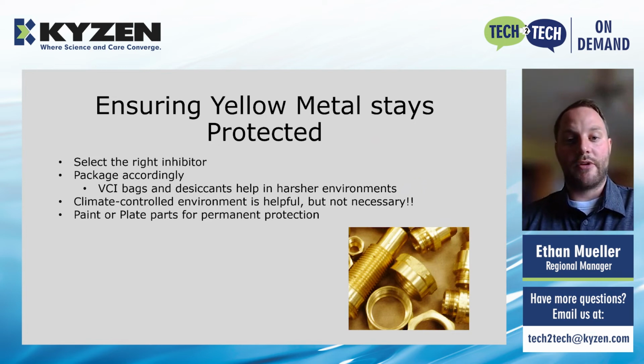And kind of the problem that you're having there is there's a good possibility that there's moisture on those parts, and the parts are hot, and so it's kind of like a humid environment trapped in a bag, and that humid moisture comes off and it condenses in the bag, and you get oxidation. So we wanna take the right steps to package our parts properly.